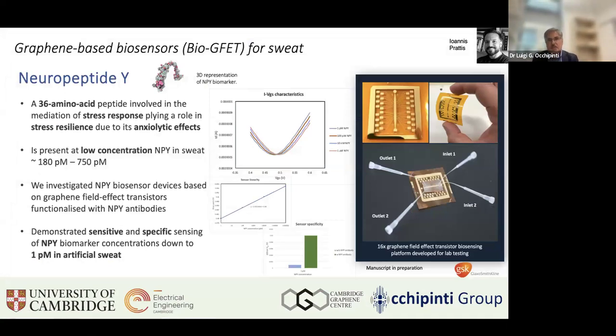More recently, again building on the same concept, we developed a project in collaboration with GSK, where we looked at one molecule, which is a biomarker of stress, which is present in sweat. The challenge here is that the concentration of this biomarker, which is neuropeptide Y specifically, is in the range of 180 to 750 picomolar, which is not really a high concentration that allows other technologies to monitor with label-free biosensors. So we decided to develop this graphene field effect transistor, where the channel was functionalized with NPY antibodies that act as receptors for the specific biomarker, and finally could demonstrate with exactly the same concept a sensitivity down to 1 picomolar in artificial sweat.